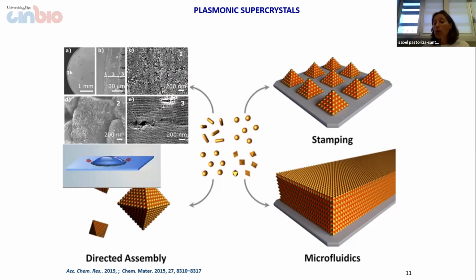In that case, the evaporation of the solvent is controlled through kinetic and thermodynamic factors, but the point is that after the evaporation, just small areas or volumes are forming supercrystals, and even the reproducibility of the supercrystals is very low. Therefore, in the last years, a new technology to prepare supercrystals has emerged, and this is the stamping.